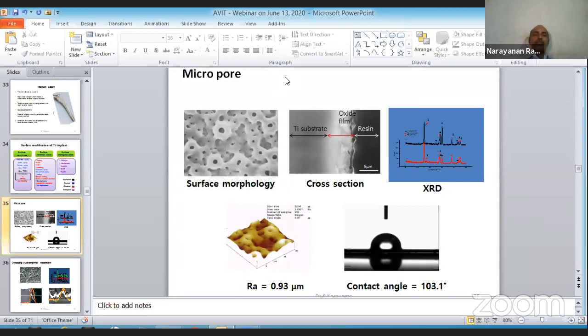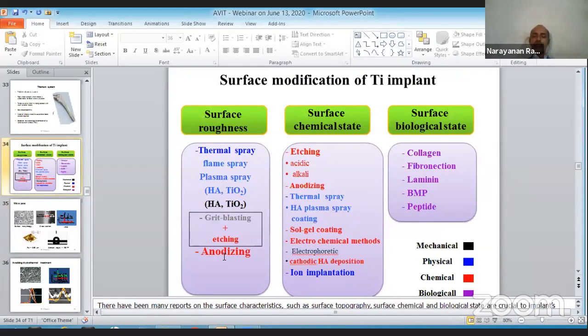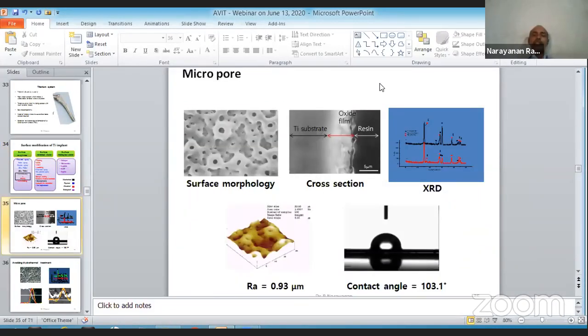Once a coating is made of an oxide on titanium, so I'm just referring to this technique. Once an anodic oxide is made on titanium implant, we have to measure certain properties, evaluate surface morphology, or whether the titanium contains an oxide film. This is ensured through X-ray diffraction. You can also analyze the surface roughness. You can see here it is high and here it is low. So the oxide is of such features. This oxide is coated on titanium. So the anodic oxide contains a certain Ra roughness, and it has certain wettability given by this contact angle.